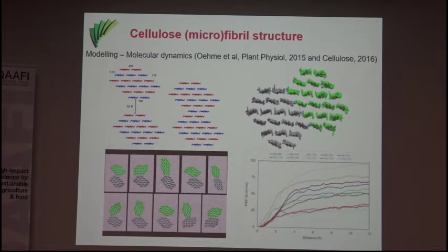But until recently, it wasn't really clear how many chains it made. We contributed to that discussion through understanding how to interpret NMR spectra and doing molecular dynamics simulations, particularly with Daniel Oehme, who was based at the IBM research facility in Melbourne, and showed that it really had to be 18. Just 6 months ago, this was much more rigorously proved by the biologists. So it's pretty clear now there are 18 chains of cellulose in an individual microfibril. But these individual microfibrils can come together.